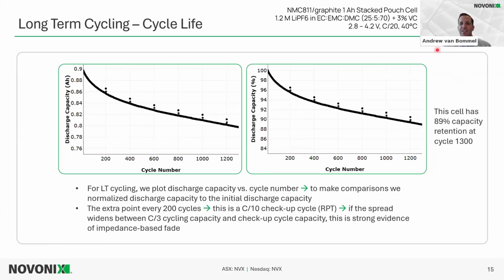So this is more of a time-based losses that would exist during the cycling. And this has 89% capacity retention at cycle 1300 for this cell chemistry. So this is very typical of the kind of profile that we'd see of discharge, normalized discharge capacity versus cycle number.